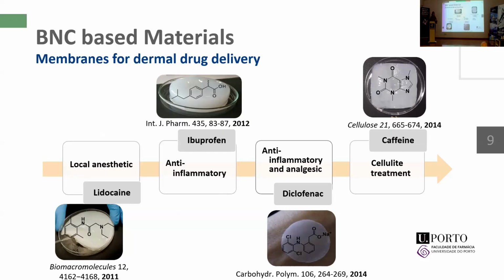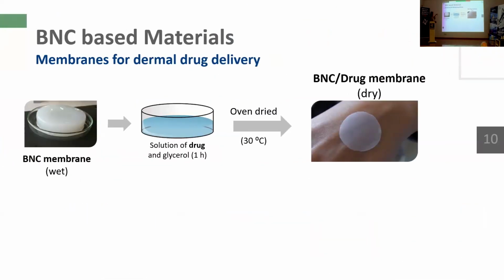We tested several different drugs following a very simple approach, just by placing the wet membranes in a solution containing the drug and also glycerol to guarantee a good malleability, and glycerol is also used as a humectant for skin formulations. And then following oven drying, we are able to obtain membranes that are very homogeneous and that easily adhere to different regions of the body.